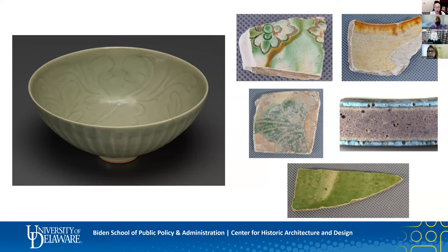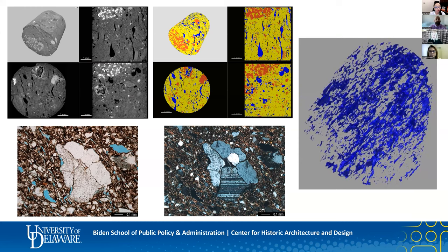Another challenge is that most archaeological ceramics have a variety of types of non-clay particles, such as organic matter or crushed rocks or sand with quartz, feldspars, micas, and iron oxides, and many other minerals present. And it's difficult using micro-CT alone to differentiate all of those different minerals from each other, and sometimes even from the ceramic matrix, since there can be a lot of overlapping densities. Identifying all of the specific particles present then usually requires other techniques. And the difficulties with differentiating many phases in micro-CT scans can limit the questions you can ask about the size, shape, and distribution of all of those particle types.